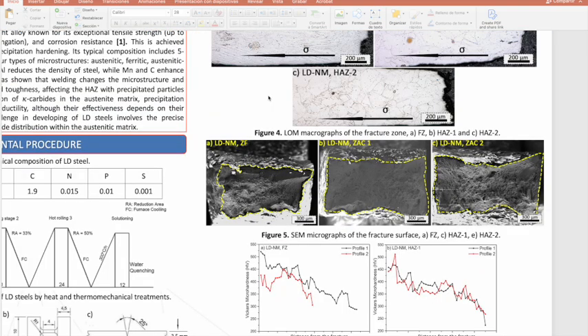Figure 5. SEM micrographs of the fracture surface: subsection A, fusion zone; subsection B, HAZ1; and subsection C, HAZ2. In general, the fracture mechanism in the different samples of low-density steel was of the ductile fracture type. The relief in the fracture surface and the low presence of flat zones can be observed. The main characteristic of the ductile fracture type is the nucleation and growth of dimples that may show coalescence.